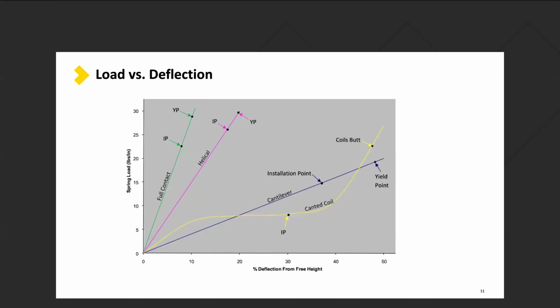So talking about the load versus deflection, this chart is general. It's not for any specific spring, but we just want to show the shapes of the curves and how the springs differ from one to another. If we look at the three linear springs, you have your full contact, your helical, and your cantilever. When I say linear, I'm talking about the curve, in that as deflection rises, force rises, and the cantilever kind of shows that the best. So as we go up in deflection from free height, our force number increases until we get to a yield point. You don't want to exceed that yield point. The spring will collapse, will no longer offer force in any direction if we exceed that yield point.